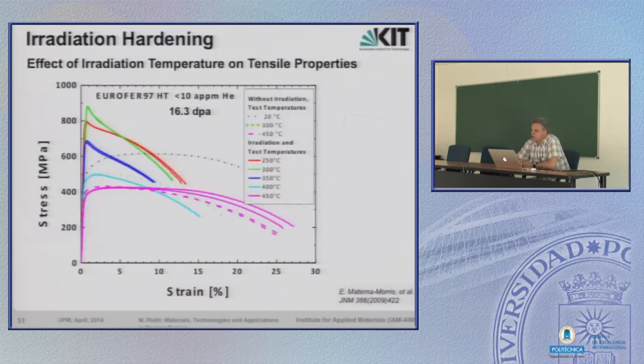This is a study of tensile properties, and this dotted pink curve is the 9% chromium steel in the unirradiated condition. And now we have to start from higher temperature, in this case 450°C irradiation temperature, and you see at such high irradiation temperature there is almost no hardening effect at all on this material. But if you go down to 400°C, then you see already the material shows a hardening effect, since the yield strength as well as the ultimate tensile strength increases. If you go further down with temperature, then the effect is much more pronounced. There is a tremendous amount of hardening.